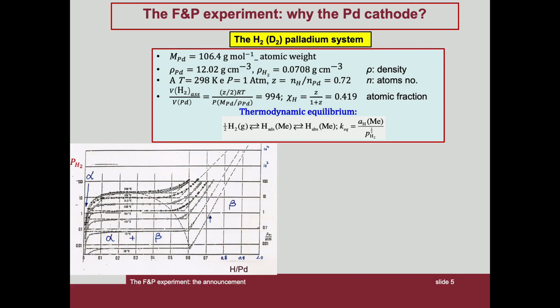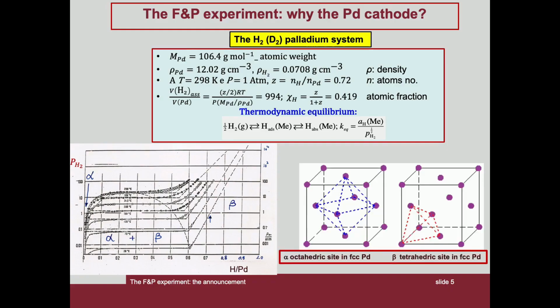Alpha phase at values close to zero of the hydrogen-palladium ratio. Biphasic system consists of alpha plus beta over a wide range of the palladium-hydrogen ratio. As the hydrogen pressure increases and the temperature decreases, one exits the biphasic domain where only the beta phase exists. The absorption of hydrogen into palladium is due to migration into the interstitial sites of the face-centered cubic lattice of palladium. Two types of sites are occupied as a function of the hydrogen-palladium ratio: octahedral sites, 4 per cell, constituting the alpha phase, and the tetrahedral sites, 8 per cell, which make up the beta phase.